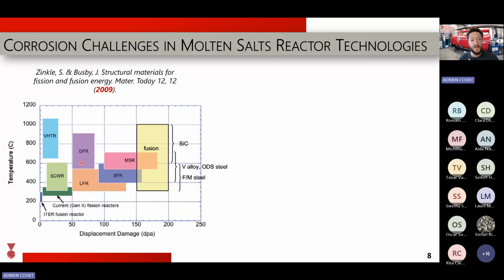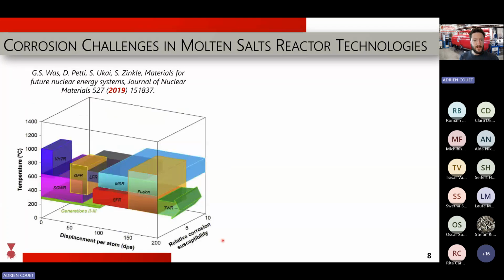So in this plot, you may recognize some acronyms. We are here interested in the molten salt reactor right there. But interestingly, you don't see corrosion in this plot. Well, that's because only 10 years later, the same group of people realized that corrosion is another aspect, not only temperature and irradiation damage, but corrosion is another aspect that limits the deployment of materials for reactors. If you look at this relative corrosion susceptibility, it's very qualitative, but you realize that the molten salt reactor, in addition to the lead-fast reactor, are the two reactors that have the most detrimental type of corrosion degradation out there.